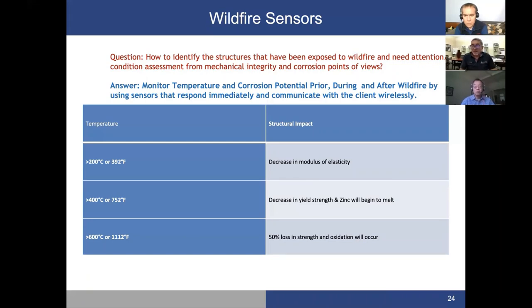So this all gives us a very important performance parameter that can indicate which structures we should look at after the exposure to wildfire. There are hundreds of structures that may be suspect. So the question is how to identify the structures that have been exposed to wildfire and need special attention, condition assessment from mechanical integrity and corrosion points of view. All along, I have been talking about temperatures, critical temperatures. So monitor the temperature and corrosion potential during and after, using sensors. That will provide for you specific sites that you need to be concerned about and pay attention to.